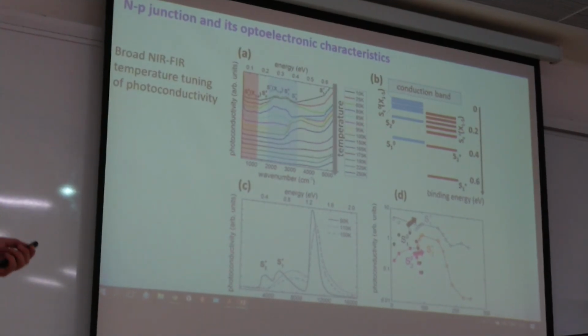And this can be illustrated here. As a function of temperature, we can see how the spectra are changing. But what is interesting here, if we have thermal ionization of, for example, this center, it becomes a state like this. So the number of states of this kind increases, and we see here as a function of temperature the photoconductivity increases in some range, until these states become thermally depleted again.